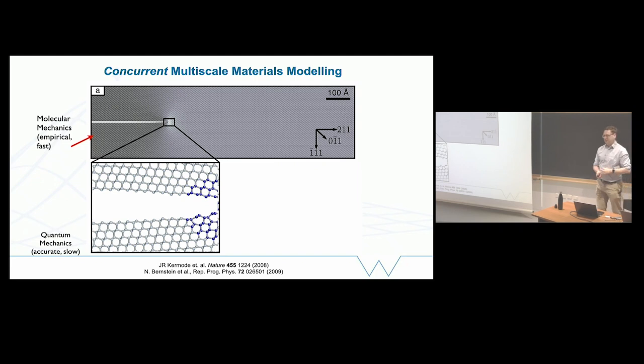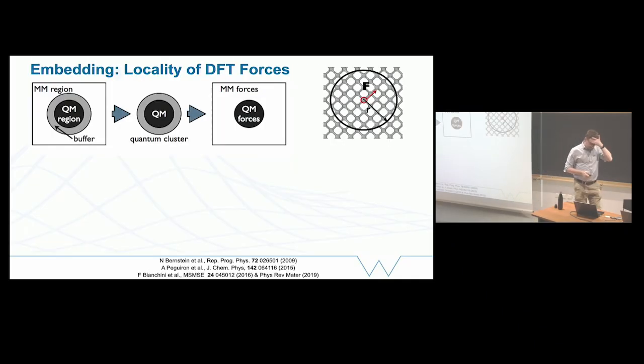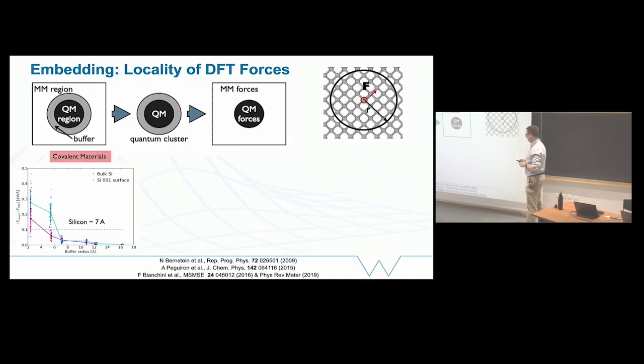We've still got a timescale problem because we're doing DFT at every time step in order to evaluate the forces on these blue atoms. I'll tell you a little bit about how that works to help get across the strengths and limitations. Essentially, we do a DFT calculation on the atoms that we care about, shown in black, augmented by an additional region shown in light gray here, which is chosen to ensure that the forces on the atoms in the black region are accurate. So we're relying on locality of forces. And then we paste together two sets of forces, the inner ones and the outer ones. We have an overall vector of forces which are more or less correct. And we can converge by making this gray region wider.